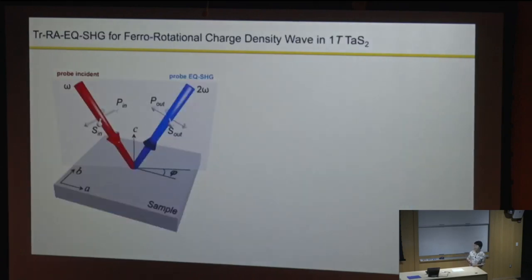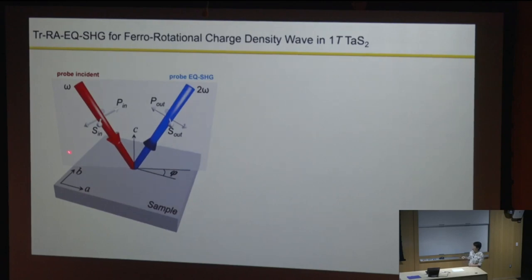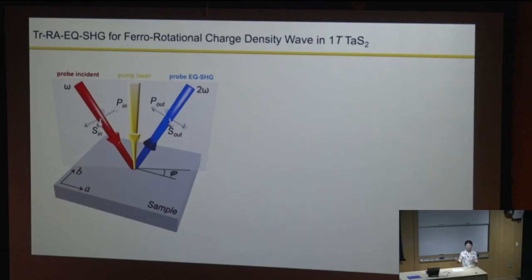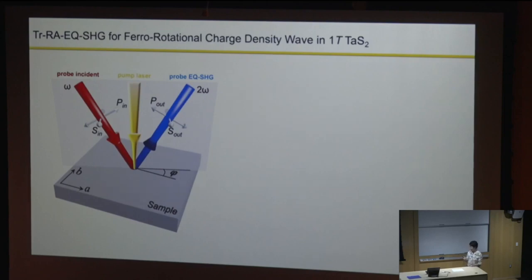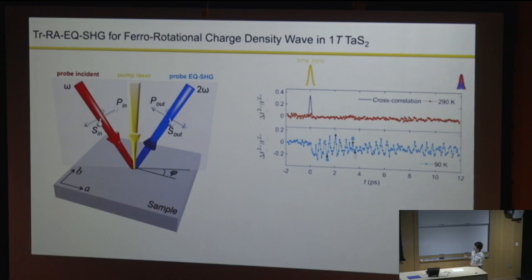After seeing individual domains, we can locate our beam into a single domain and measure its dynamics. We still do the same probe procedure but introduce a pump beam that excites the material, then do the same measurement of the probe at different time delays. You can see when the order forms—clear oscillatory behaviors appear, very often seen in time-resolved optics, especially in time-resolved reflectivity when people see phonons.